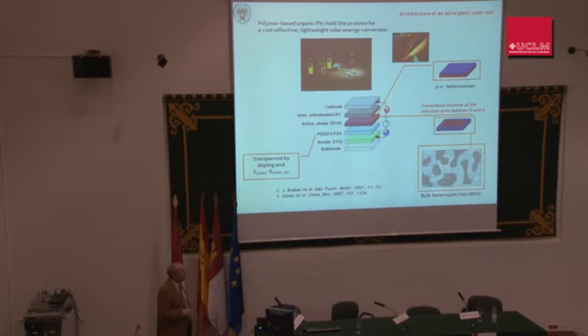So it is almost 20 years since we started with these topics. This is a tremendous increase of the interface area between donor and acceptor. This is intertwining donor and acceptor species, and therefore, in principle, it should dramatically increase the interaction at the interface. This could be considered the fullerene and the polymer in between.